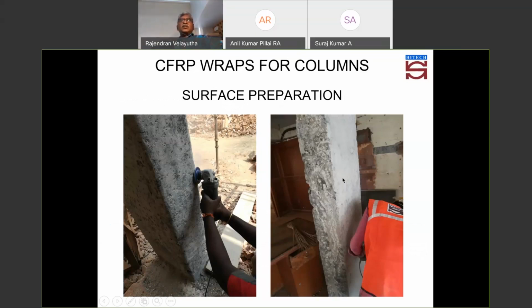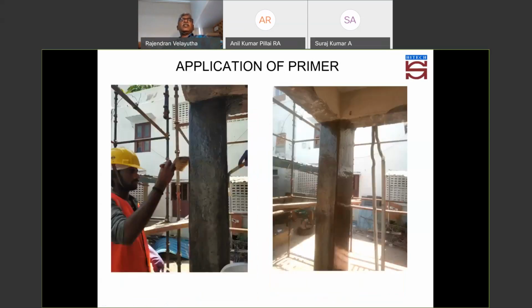It's going to be a pakka zero-zero, because the bond between the FRP system and concrete is very, very important. If there are a few holidays, then that's not going to be a proper bonding. And when there is no proper bonding, the adjacent area will have stress concentration, and there is every possibility the FRP system can get delaminated. Once it gets delaminated, the whole purpose of the rehabilitation system fails.